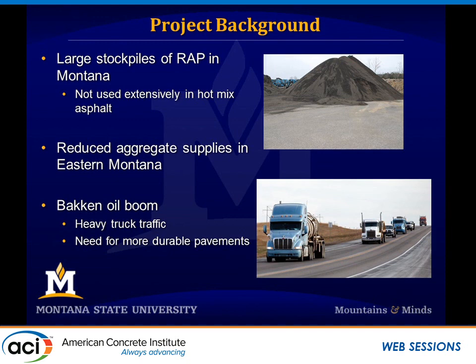Other states are looking at using RAP. Illinois just finished a study to use RAP in their concrete pavements, and one of the reasons for that is they're using their fine aggregates in hot mix asphalt, but their coarse RAP they're not using everything, and so they have big, giant stockpiles of coarse RAP. So the outcomes of this research could be further reaching than just Montana.